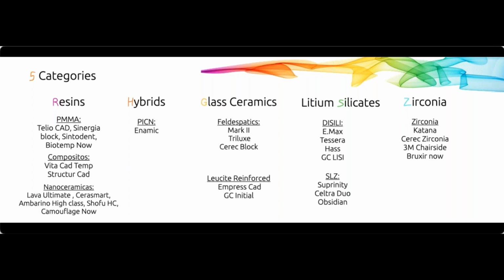Hybrids, there's only one in the market. It's a piece of glass that resin was infiltrated inside of. So what it did is it brought the modulus of elasticity from being a material that is very stiff to something that will work nicely on top of dentin. So now when you have a preparation with enamel and dentin, you bond this and it will behave better, especially on the forces that go to the bonding layer, that tend to receive stresses when there is a mismatch. You get debonding, secondary decay and leakage.